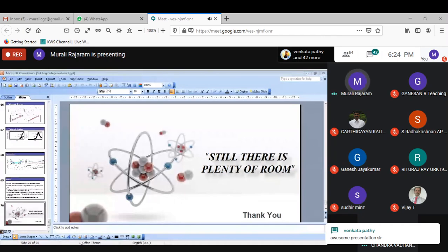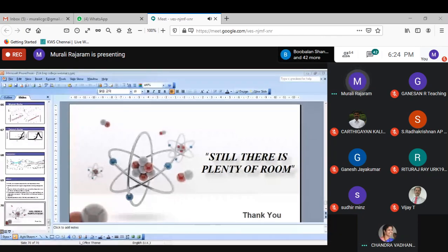You can grow your composition, especially when I consider these nanocomposites, I feel pulsed laser deposition is better than sputtering, because the growth rate affects the interface property, the elastic coupling. So I feel that PLD is a better option for this kind of nanostructure. There are reports on sputtering also.